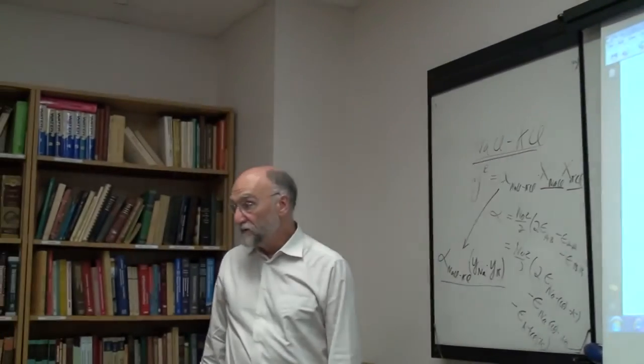Now, how is that going to be weighted as you start to add fluorine? Well, this is the energy of a sodium-potassium bond when they're separated by chlorines. This is a sodium-sodium bond separated by a chlorine. Potassium-potassium bond separated by a chlorine. The number of each of those bonds will decrease as you decrease the number of chlorines.